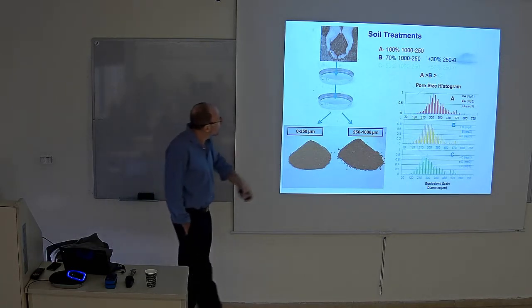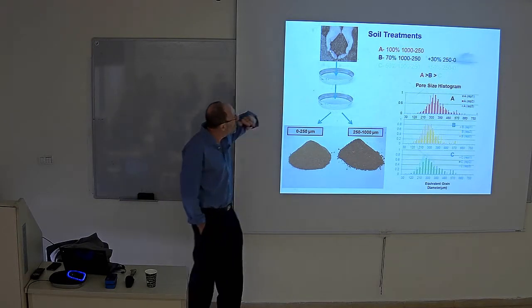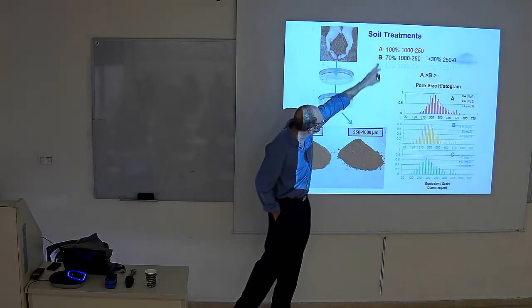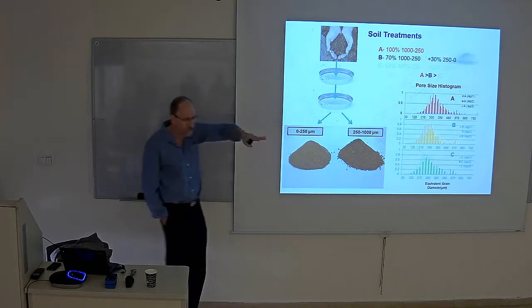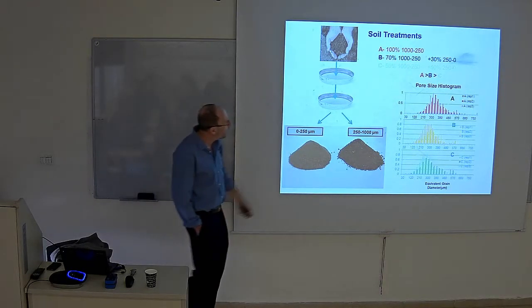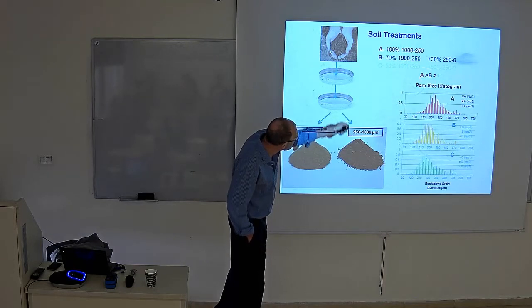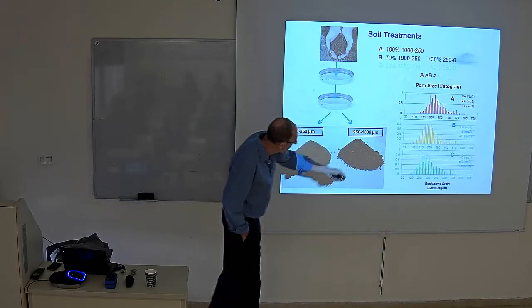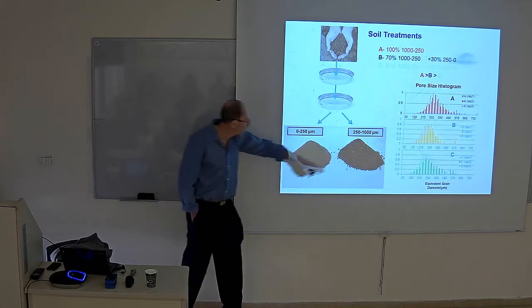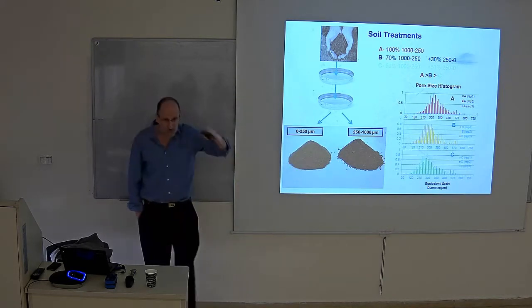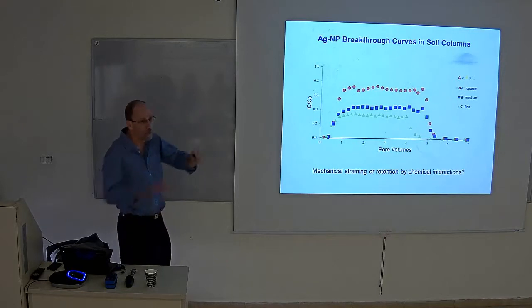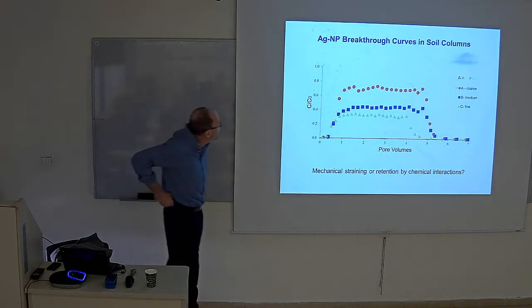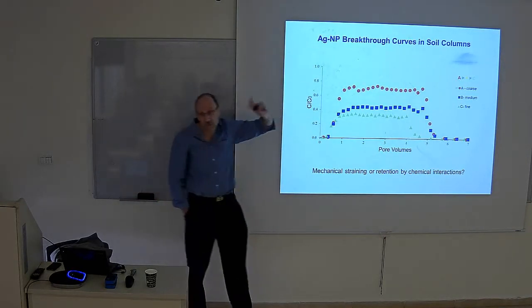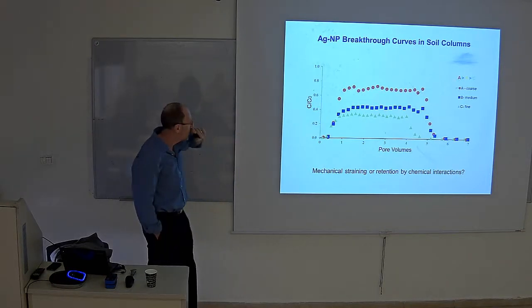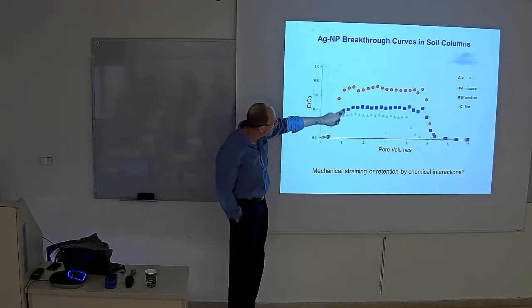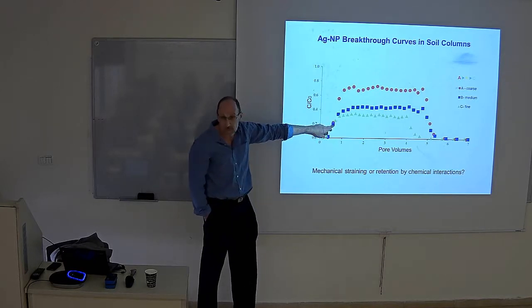Okay. So one of the experiments we did, we took soil, also from Bet Dagan. It was filtered, or what do you call it? Sieved, into different sizes. So it's enough to know we had different pore sizes, or different grain sizes, or different fractions here from 1,000 microns down to 250, so we took 3 different fractions, took columns with each of these different fractions and said, okay, let's just take silver. Silver is supposed to be non-reactive, at least at the time thought to be non-reactive. And in the coarse, medium, and fine sands, here's the breakthrough that we get for a pulse.